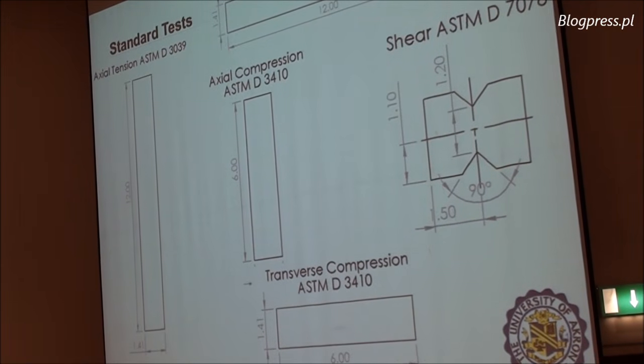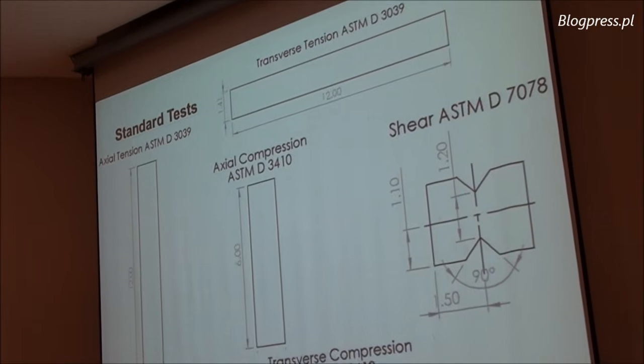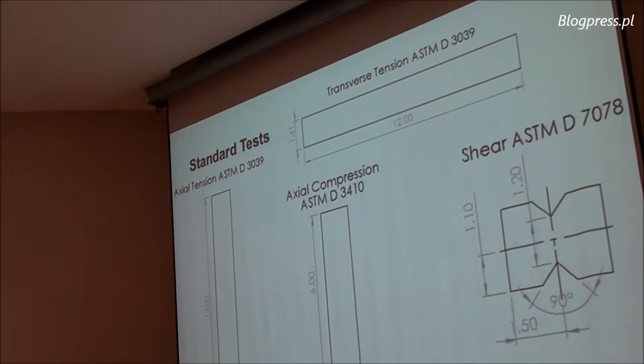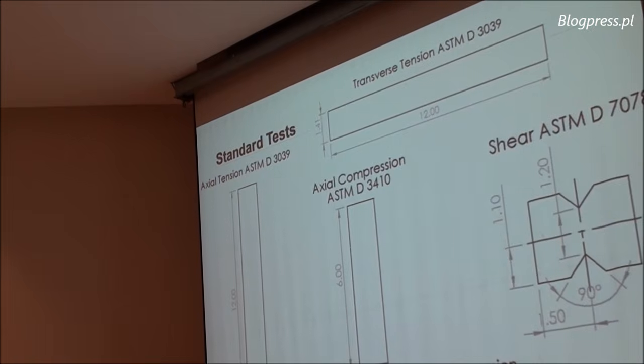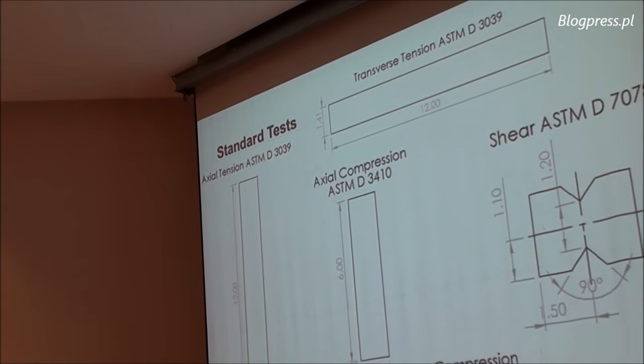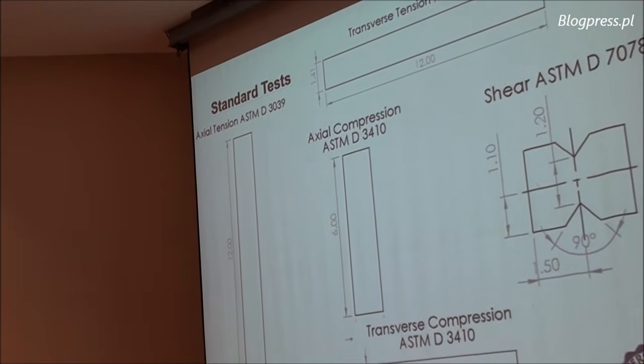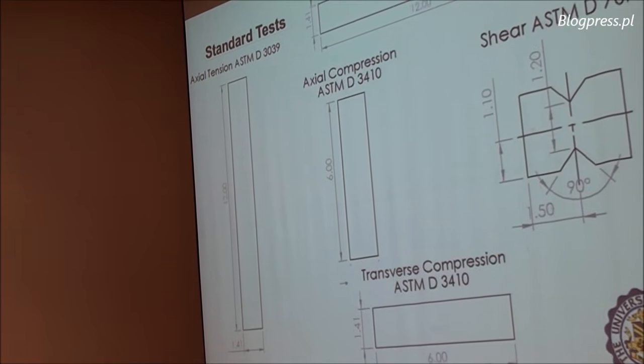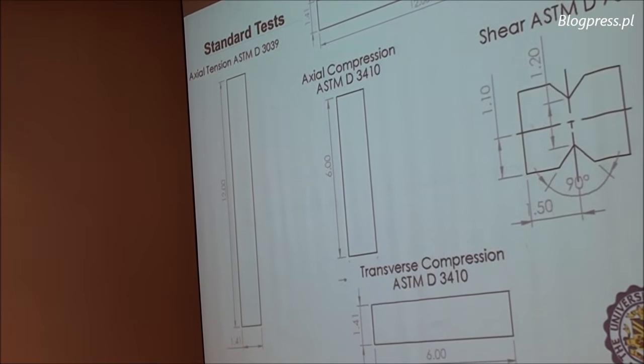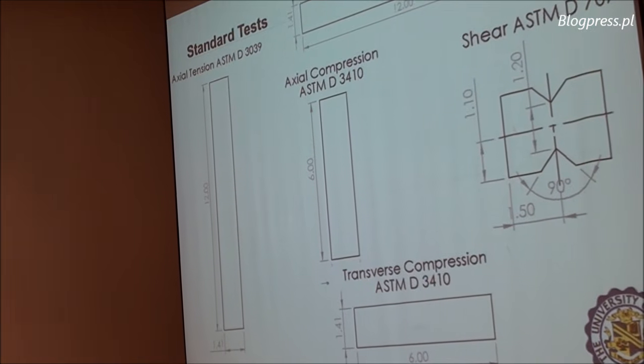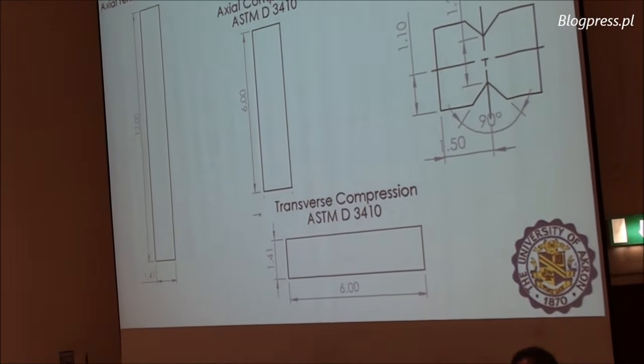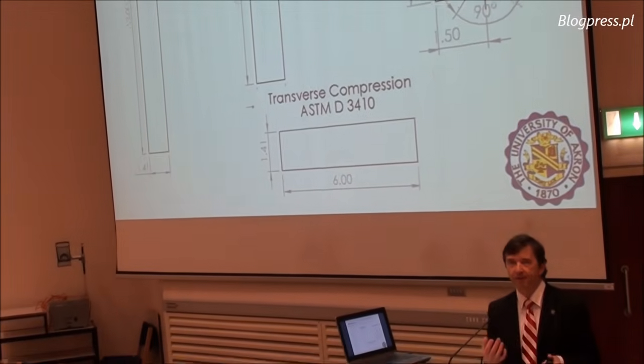Of course, from the testing point of view, there are ASTM standard tests. I don't know what test you use here in Ireland, but in the United States, ASTM is the way that we follow. Unfortunately, this is a coupon of the simple tensile test, and you can see that the edges, these outside edges, basically cut through the bundles that are plus minus 60. And this has, we found, a consequence on the results of the tests.